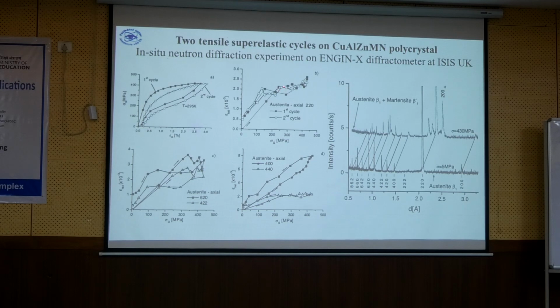But when martensitic transformation starts, here it doesn't increase anymore. So you have such a response of the lattice spacing of the 220 peak. But if you take another reflection like 400, you will get a response which is completely different. And again here, completely different. So what does it mean? This somehow gives the information how the families of equally oriented grains transform during the loading. So this is the information which no one can obtain from stress-strain experiments.